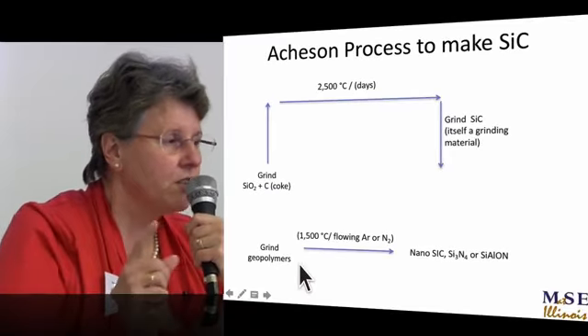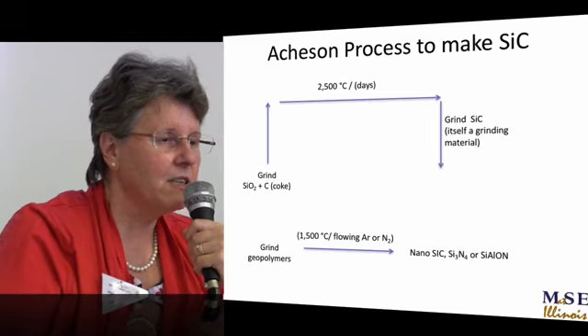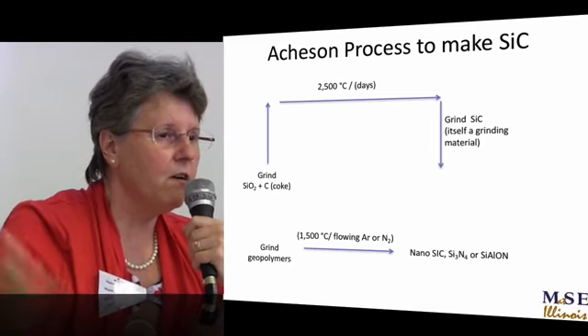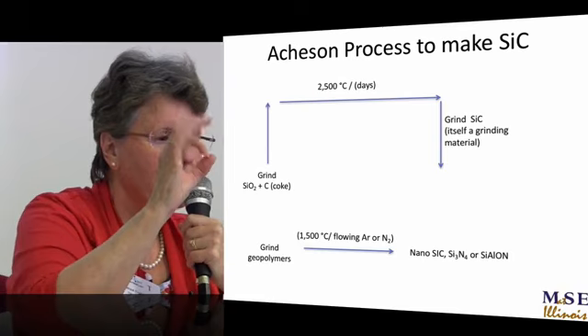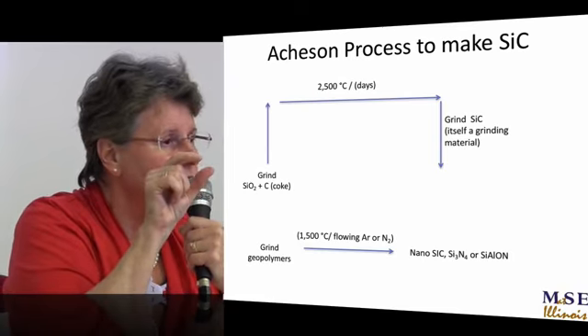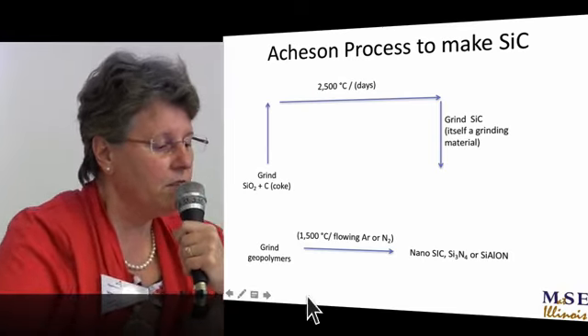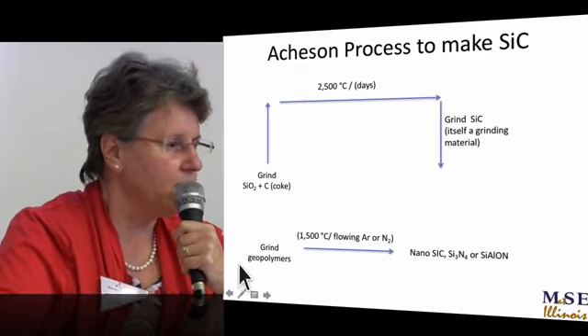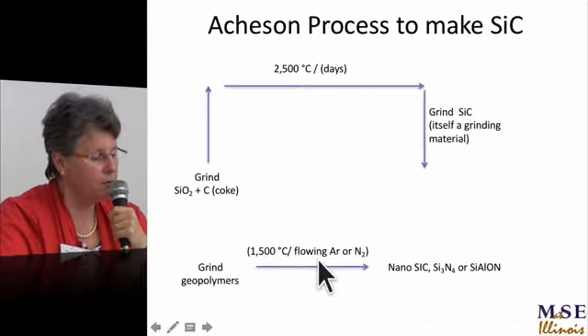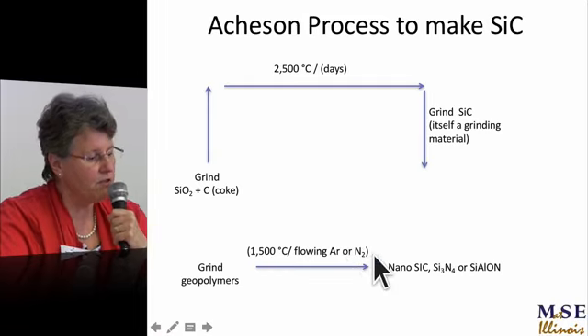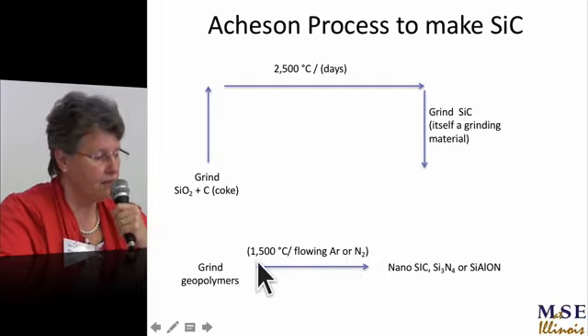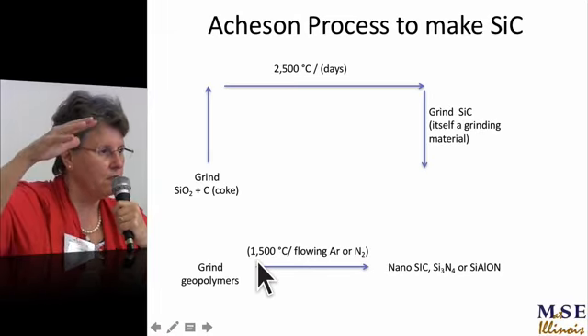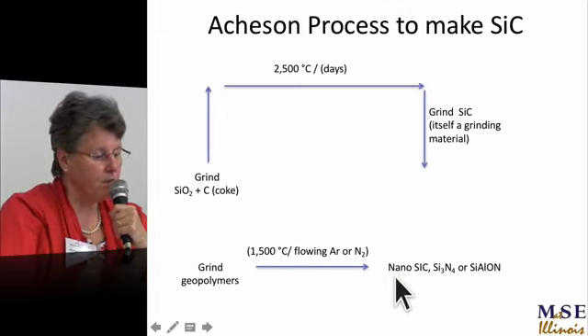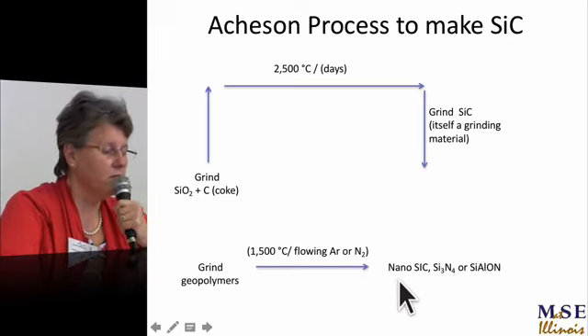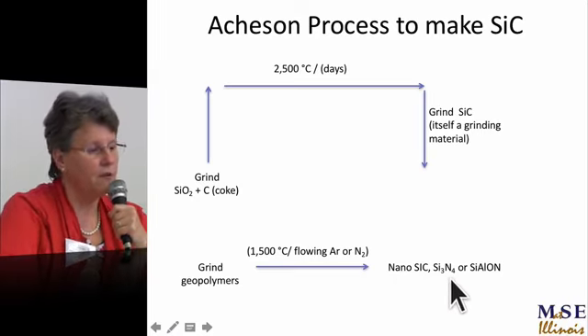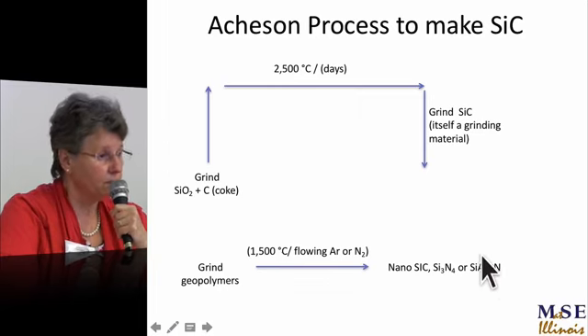Meanwhile, the trick is geopolymer makes nanoparticulates, right? Well, go with the flow. If you have a nanoparticle, the diffusion distance is very short, small. So you get some geopolymers and you grind it. It's not as hard as silicon carbide. And then you put it in flowing argon or nitrogen. We did 1400, 1500, 1600, 1 or 2 hours, and you get nano silicon carbide, silicon nitride, or SiAlON.